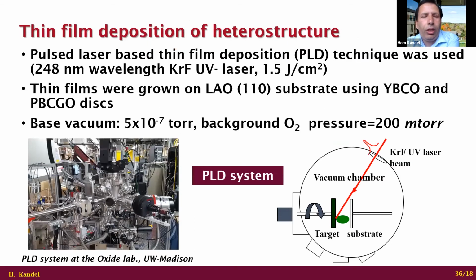Next slide, please. So we use a pulsed laser-based thin film deposition system, what we call in short the PLD system. This is the system that we use at the oxide lab at UW Madison, and behind this vacuum deposition system is a laser production unit. On the right-hand side, as you can see, is the schematic diagram of this pulsed laser deposition system, where we use a high-power UV laser. We strike the target material, such as YBCO and PBCGO, then evaporate and create the plume, also called the plasma, and allow it to condense on the single crystal LaAlO3 110 substrate on the other side, which is also heated at a high temperature, somewhere between 700 and 800 degrees Celsius. By setting different parameters, we can control the properties of these heterostructures.